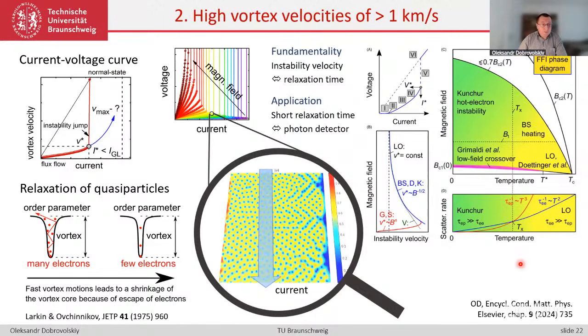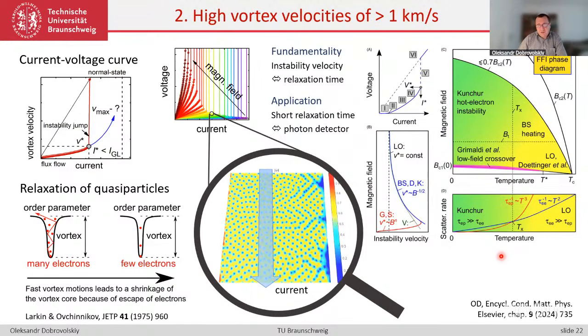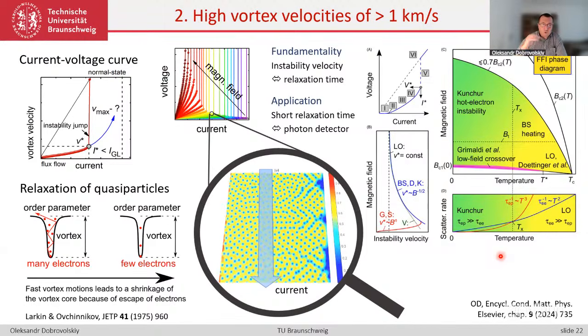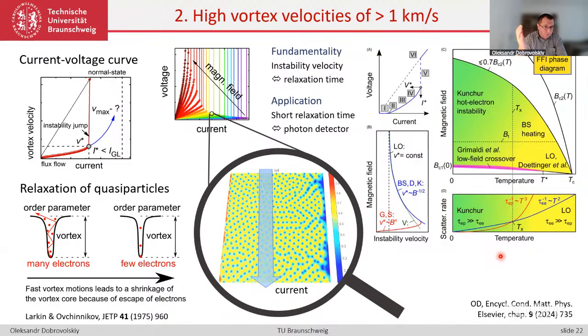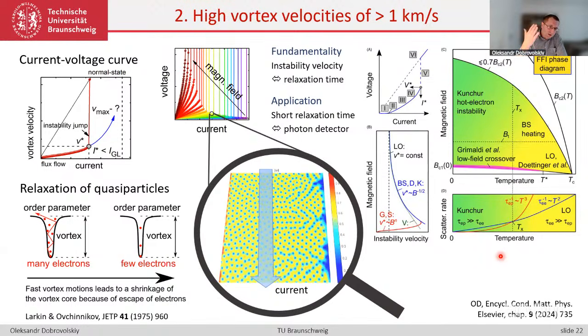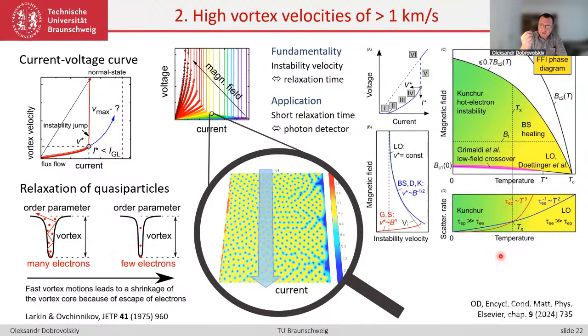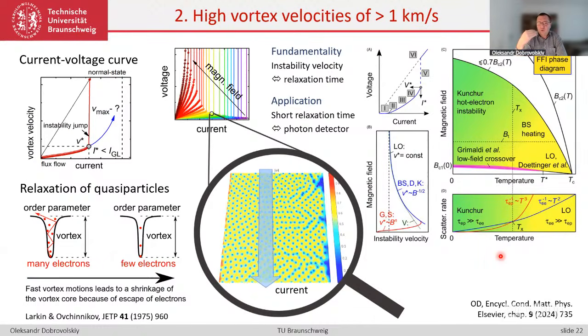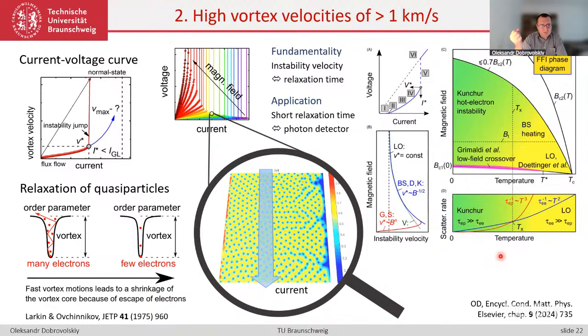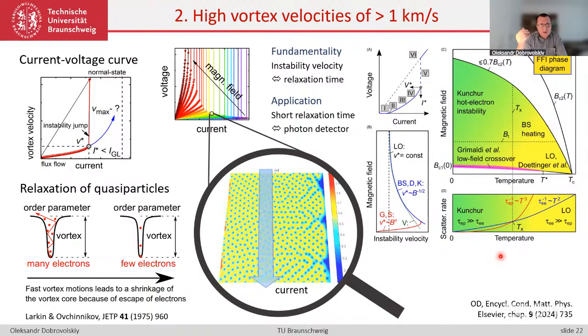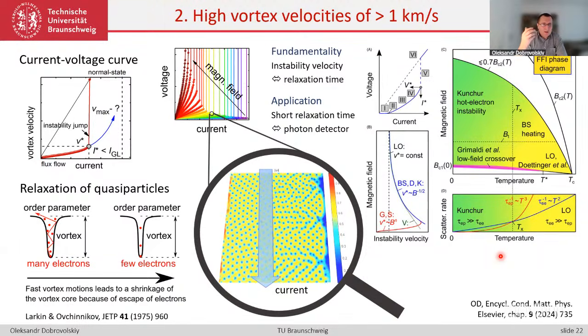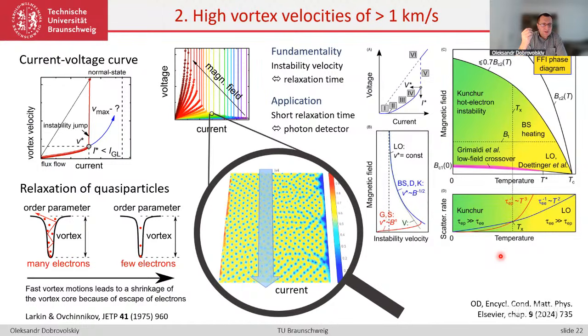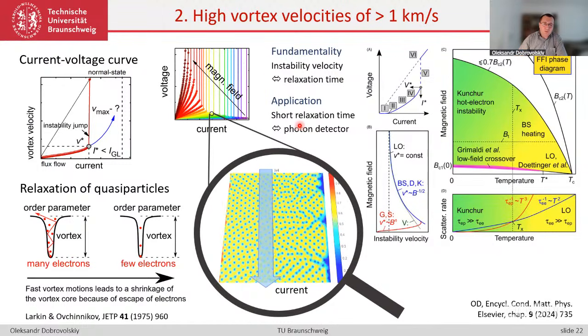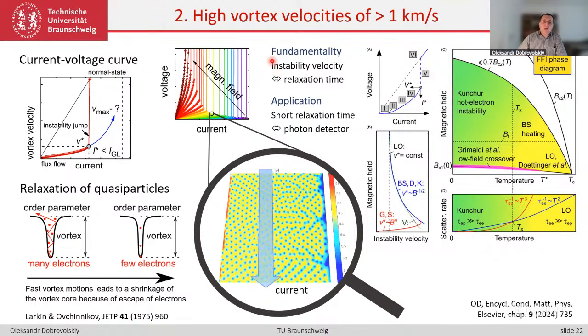But the idea is that in principle, it's possible to tune the quasi-particle relaxation time and to operate with one of them dominantly. For instance, the electron-phonon interaction close to Tc, or the hot electron regime, with electrons dominating the scattering, far away from Tc; to use superconductors with very strong and close to ideal edge barriers for ordered vortex motion; and in general, dirty limit superconductors, which are materials of choice for photon detectors, as stated here.